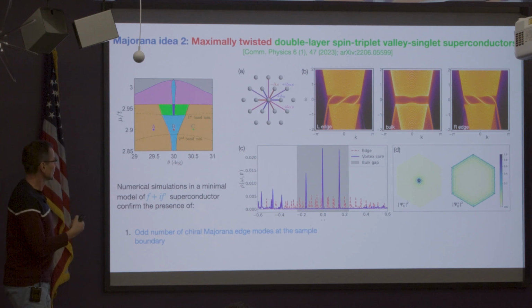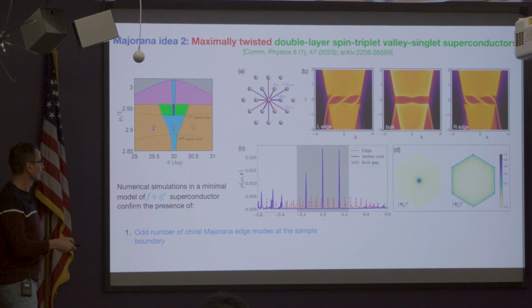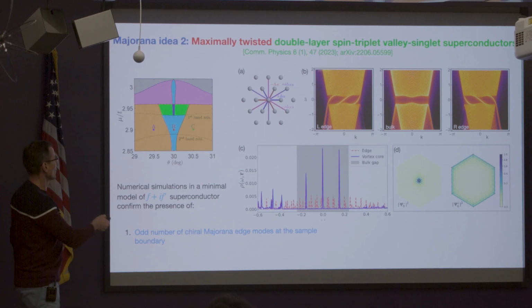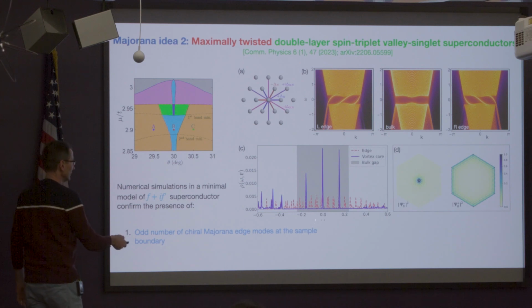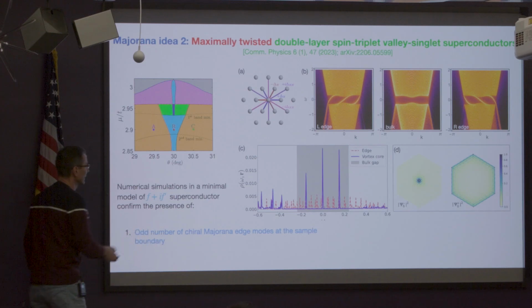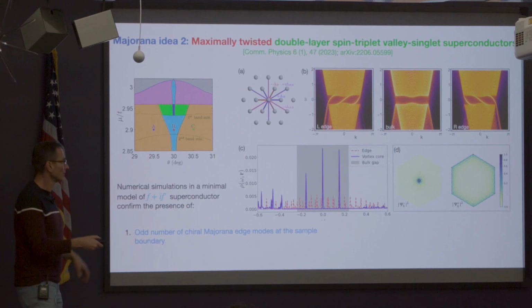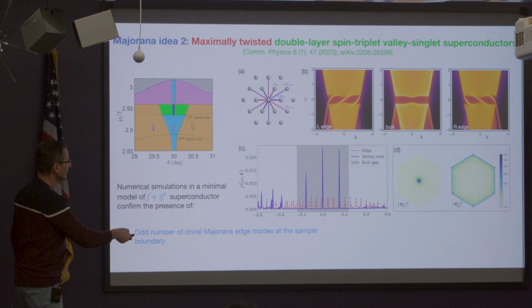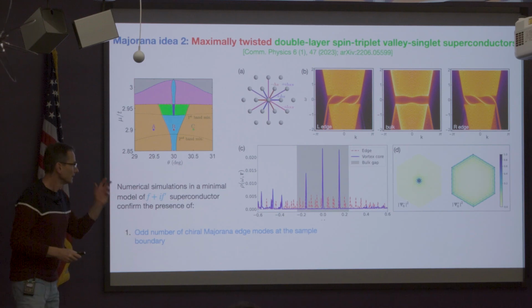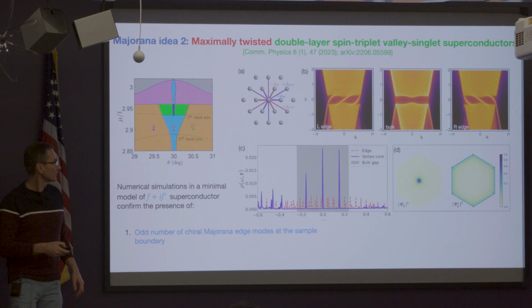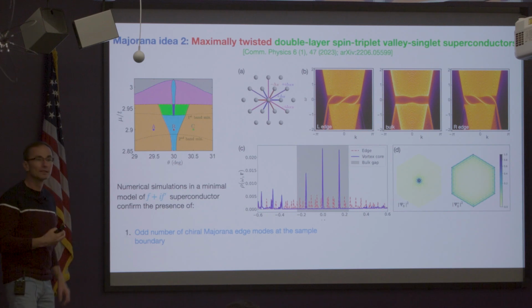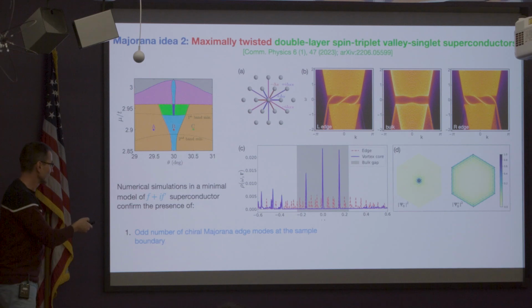And just to make completely sure, we've done a simulation for a vortex. So basically, we put this model on a hexagonal domain like this. We put a vortex in the middle. And indeed, what we see is a zero mode. In fact, there are two zero modes. One lives at the center, one lives at the boundary, and you can run various checks to see that they are self-conjugate in terms of their wave function, so they are indeed Majorana zero modes.